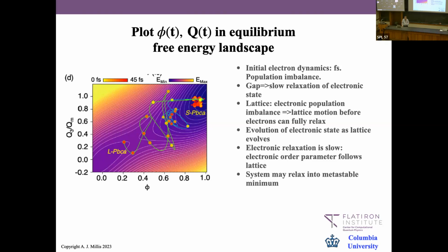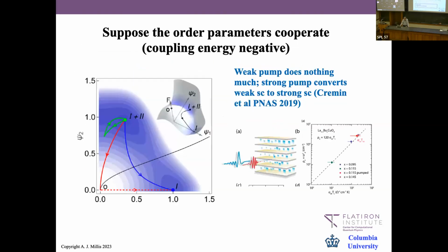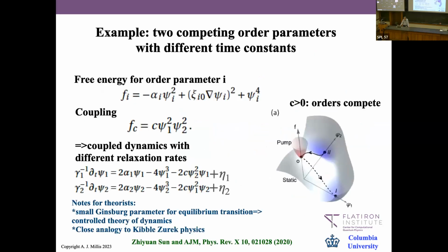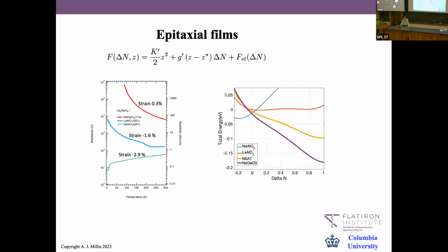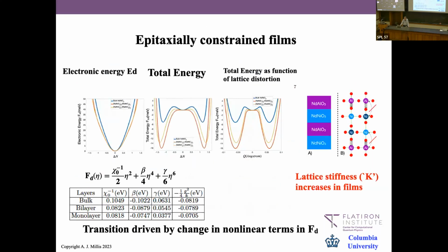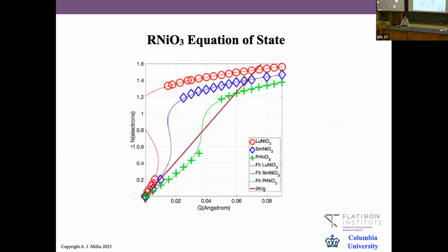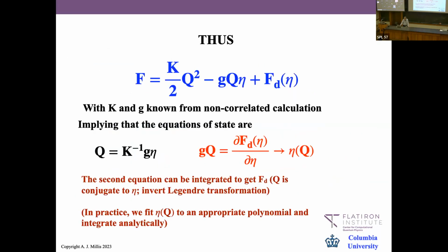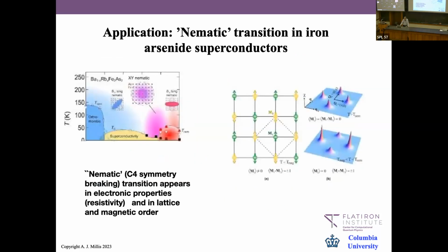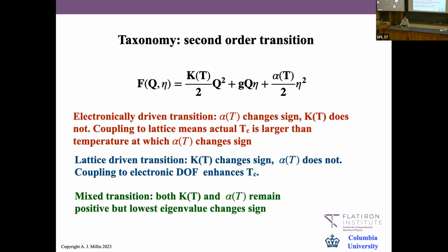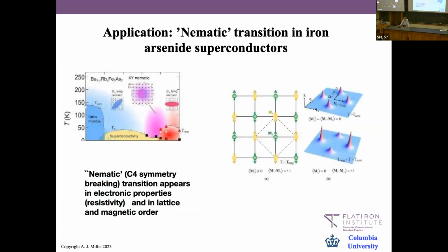So if I understood things right, still in this equilibrium picture of these energy landscapes, when you couple these two order parameters, essentially one of them dresses the effective TC that you get. And it seems you universally get that this TC goes higher, whereas I would expect that when I couple to something else that could fluctuate, it should promote entropic forces and should drag this TC down. Is that just a matter of the sign of the coupling or something else?